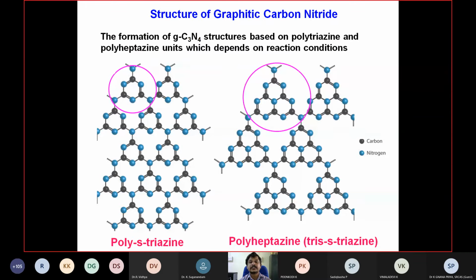You can see the structure. The first one is the triazine-based structure. The second one is the heptazine-based structure. When comparing the stability of both cases, the heptazine-based graphitic carbon nitride is more stable because you can see the extended double bonds are more here, but here the double bonds are very few, only 3. But here there are almost 6 double bonds within a monomer unit. That's also the thermodynamic factor, and theoretical studies also reveal this material is more stable than this material.